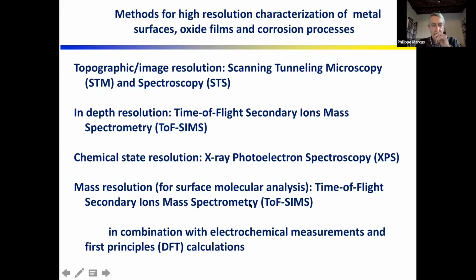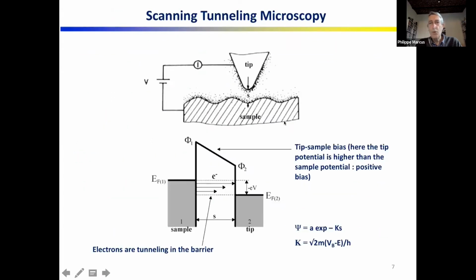And as I said in the introduction, we combine these techniques with electrochemical measurements and in many cases with DFT calculations. So among these techniques, I will show results that were obtained using scanning tunneling microscopy. So a brief reminder, in this technique, we bring a metallic tip close to the surface, and if the tip is close enough, electrons can tunnel from the tip to the sample or from the sample to the tip.